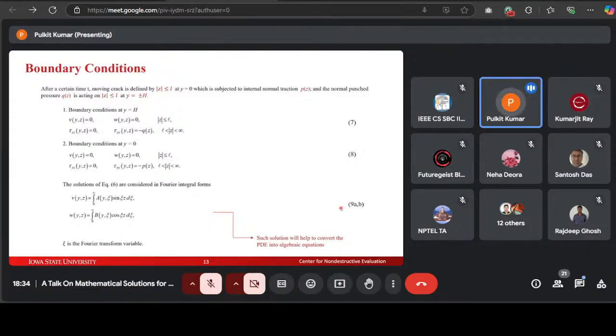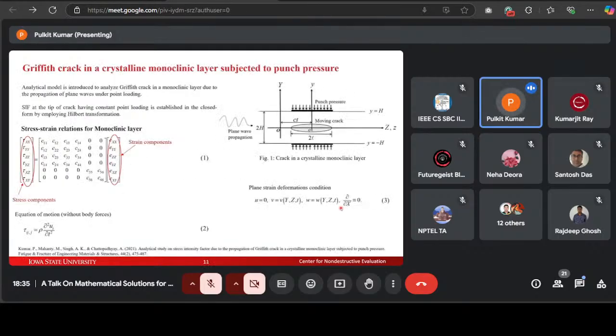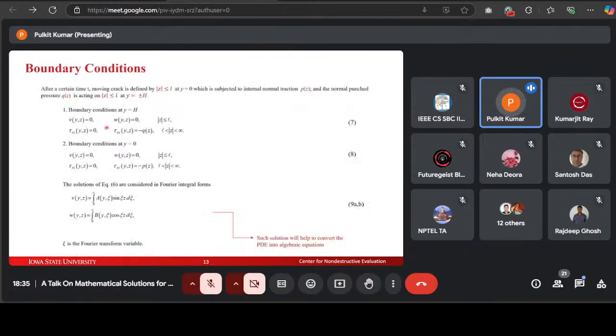Now, for the boundary conditions, we will go back to the geometry of the crack propagation. After a certain time t, the moving crack is defined by mod of z less than or equal to L at y equals 0, which is subjected to internal normal traction P of z, and the normal punch pressure, which we denote by Q(z), is acting at mod z less than or equal to L on both the surfaces y equals h and y equals minus h, which is defined here.